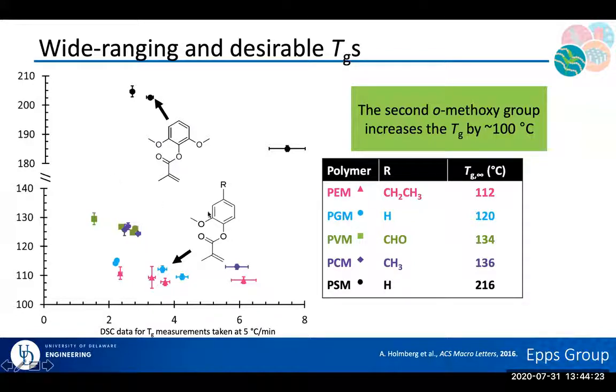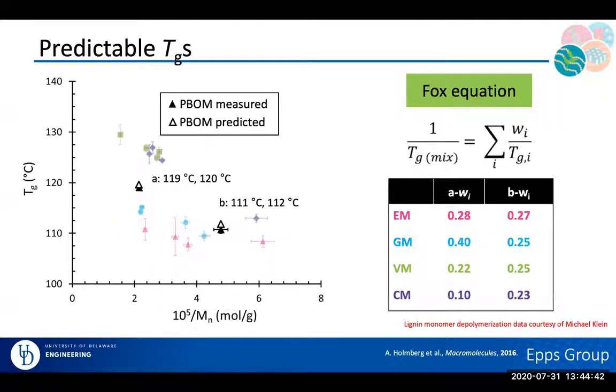The other thing that I'll point out, because I'll mention this again in the next slide or two, is that they're both methacrylate functionalities, meaning that we should be able to co-polymerize to basically target any glass transition temperature in this range and tune it for various applications. Now, one of the nice parts about that is that we can actually make those copolymers, and then we can do some really neat studies.